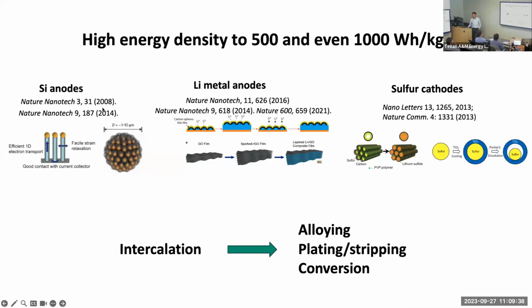My lab has been an early pioneer in the development of silicon anodes, lithium metal anodes, and sulfur cathodes, also phosphorus anodes as well. These offer you about 10x the charge storage capacity compared to current technology. They can potentially double or go to 4 times the energy density. It's a shift from the intercalation mechanism to alloy mechanism, plating and stripping mechanism, and conversion reaction mechanism. Completely different from the Nobel Prize winning work back in 2019.